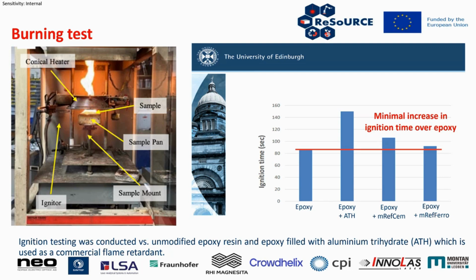So on the right-hand side there, we've got the graphs of the raw epoxy, epoxy with aluminium trihydrate, which is the commonly used filler for flame retardant coatings, and then along with our mRefCem and MREF ferro materials. So you can see we do get a slight increase in the time to ignition compared to the raw epoxy with our materials, but it isn't as good as the industry standard aluminium trihydrate. These are all initial look tests. These are not the full sweep of what's possible.